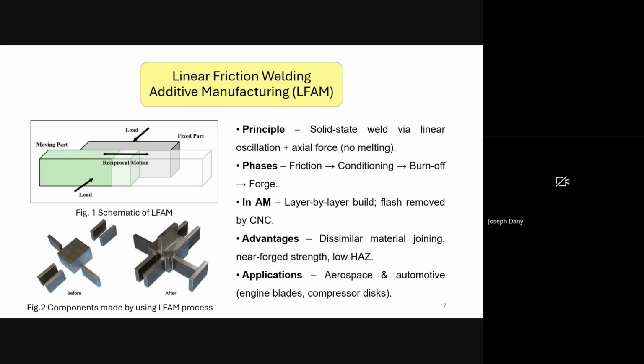The linear friction welding process can be divided into four distinct phases that ensure a strong and defect-free joint. The first phase is the initial contact and friction stage, where the relative sliding motion causes microasperities on the surface, increasing the real contact and starting initial heat generation. The second phase, called the transition and conditioning stage, is where the surface layers and oxides are expelled and a fresh plasticized layer forms at the interface due to frictional heating. This stage is crucial as it promotes clean metal to metal contact, which improves weld integrity.